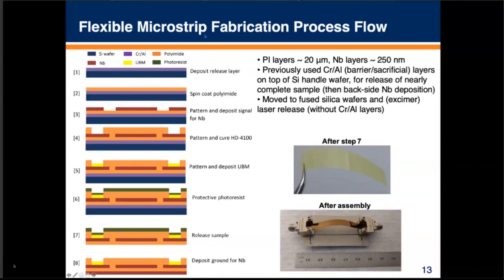In terms of the microstrip fabrication processes, we would go ahead and just release this by chemically dissolving away the aluminum layer. We would release this structure, and then we could deposit a ground on the backside. And you can see what some of these structures look like here. I'll mention later on some of our more advanced fabrication processes.